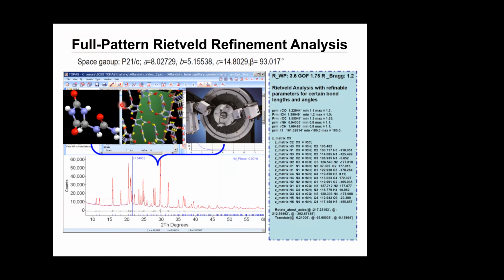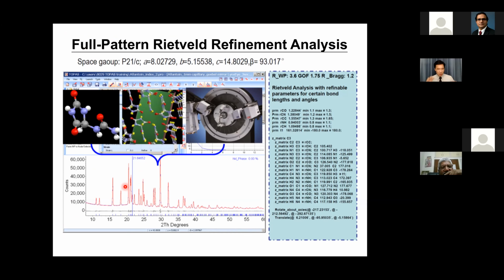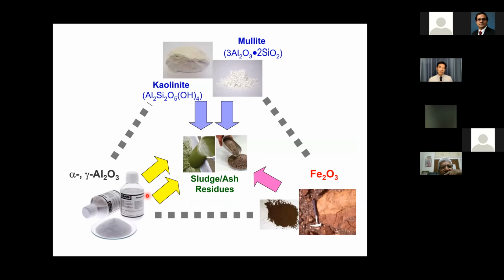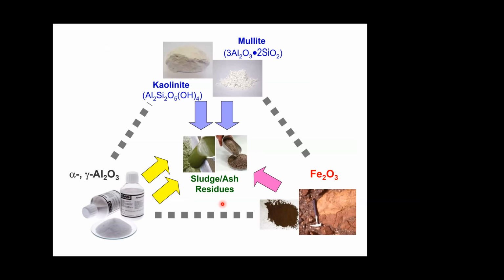These days, we don't sit down and calculate by hand, because the actual profile could be very complicated, with multiple phases. So we use computer simulation. It's in fact simulating the atomic structure, building atomic structures as the basic model, and you use these basic models in combination to fit the profile that we observe in the system. Then you know the amounts of the different phases represented by the different standard profiles. So that's how we start. First of all, let's put the heavy metals mixed with kaolinite, mullite, gamma and alpha alumina, even with iron oxide, and see what the basic reactions are.